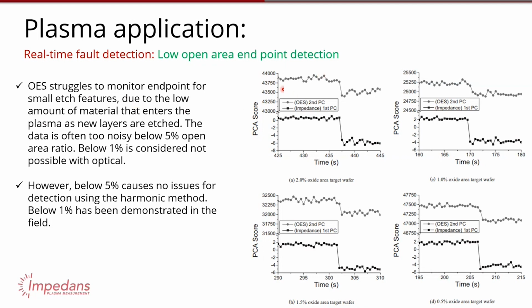But with RF, there are publications saying you get at least twice the sensitivity. From my own experience, on chambers where optical struggles to get below 2% of the wafer being monitored, we've demonstrated well below 1% or even below 0.1% of the wafer being etched. Again, through this capacitance change of the wafer, and the corresponding harmonic and phase changes, you can judge that the etch is done and the endpoint is reached. So I think this will be very powerful for the industry going forward. I will stop there and open it up to questions.